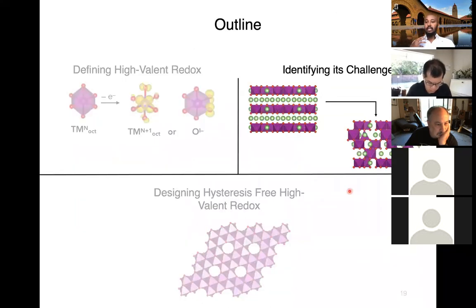So this brings me to the second part of my talk, which is trying to understand this challenge. The challenge here again is the hysteresis that causes energy loss whenever we have anionic redox. And we want to understand what is the mechanism and what is the source of this hysteresis in order to be able to avoid this challenge. So we use several techniques to be able to answer and understand these challenges. The one technique that I'm going to heavily use throughout my talk today is called RIXS. RIXS stands for resonant inelastic X-ray scattering. It's a method we use to characterize the electronic structure of the material.